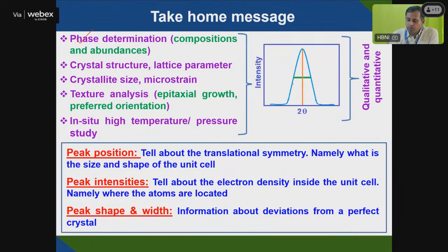Second, by using peak profiling, with full width at half maximum, you can get the crystallite size, and then the lattice parameter by using that equation, whether simple cubic, FCC, or BCC.